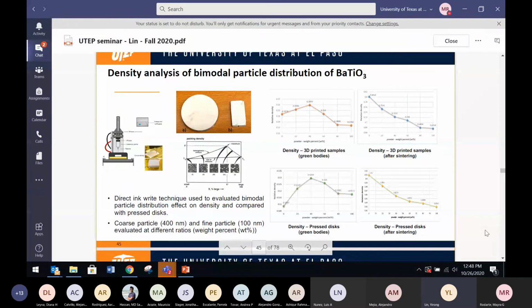Okay, so this is an interesting thing we're trying to do. As you see, we do a lot of hands-on experimental work, right? A lot of times we're just doing trial and error. So we're trying to have some modeling to control or guide these experimental processes, right? One of the things we did is look at particle size distribution, controlling the properties, right? As we know, if you use bimodal particle distribution, it gives you the best packing density. But after sintering, it's a different case.